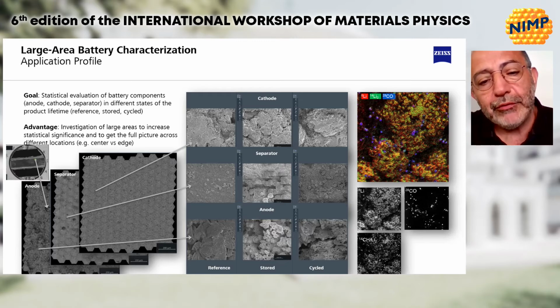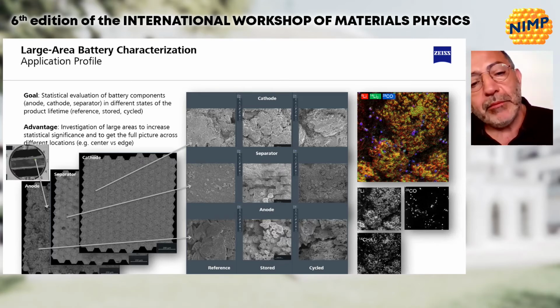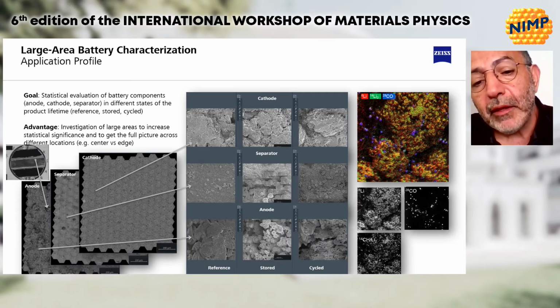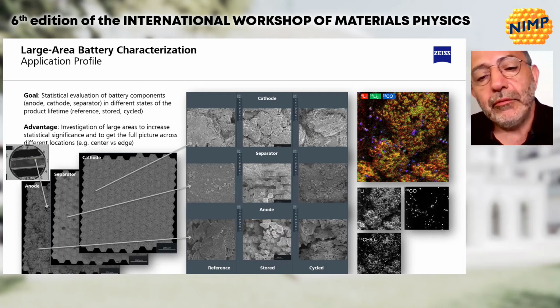And why is it so important to have this kind of instrument? Just to give an example or an estimation, if you try to do a scanning of a square centimeter of sample with nanopixel resolution, it will take weeks, only beam time scanning. But using this kind of multi-beam approach, field emission SEM, you can reduce the scanning time by 2 orders of magnitude. It means you will finish in a couple of hours of scanning time instead of weeks. This is just to give you the instrument needed in order to perform this huge context